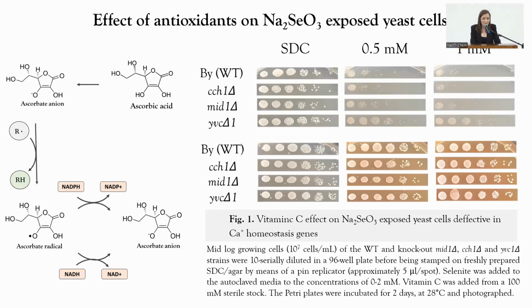We have tried to find out if there is a way to preserve the selenite reduction, but also to mitigate the potential unwanted effects on yeast cell growth. And so we assessed the effect of some antioxidants on sodium selenite exposed cells. We started with vitamin C. We added vitamin C to a sodium selenite enriched media. And when we prepared these agar plates, we noticed that the addition of vitamin C instantly reduced our selenium precursor sodium selenite, and therefore the media turned red.